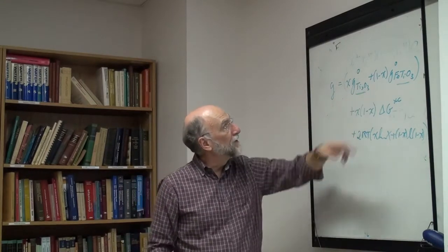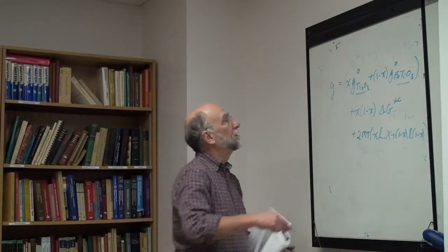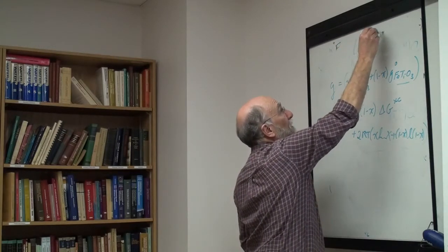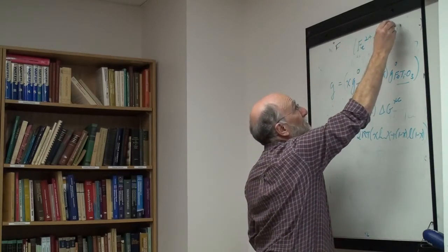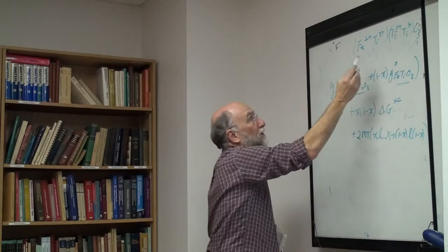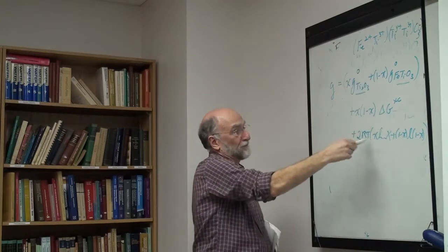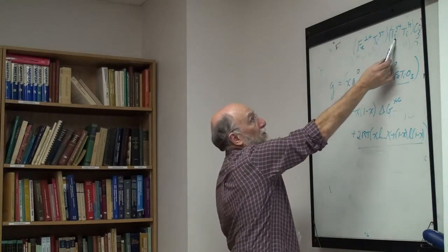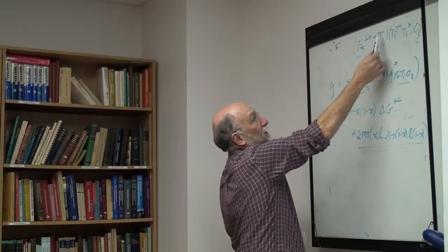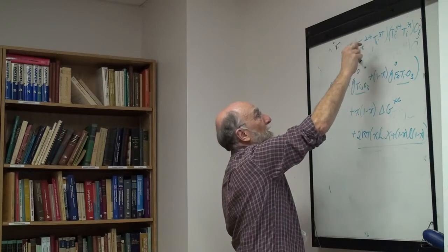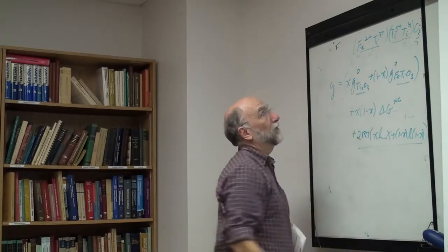You're mixing titanium. Going back to this, it's Fe2 plus, Ti3 plus, Ti4 plus, Ti3 plus O3. Here, an ideal mixing term is simply an ideal mixing of Fe2 plus and titanium 3 plus mixed randomly on one site, Ti4 plus and Ti3 plus mixed randomly on the other site.